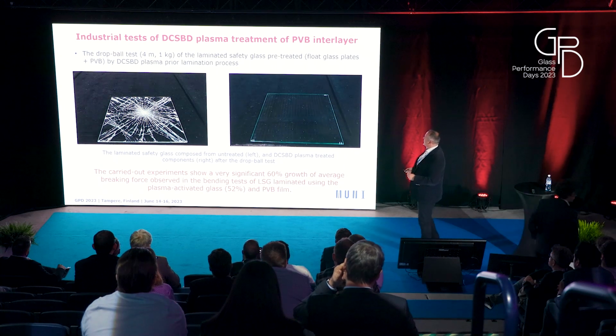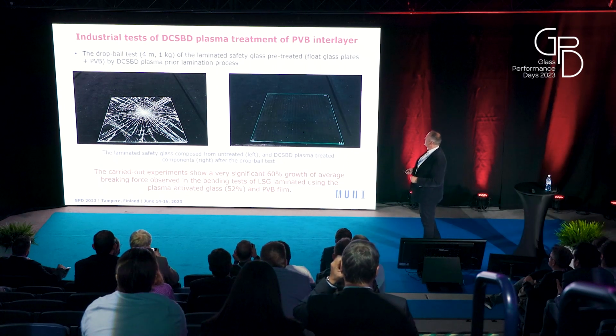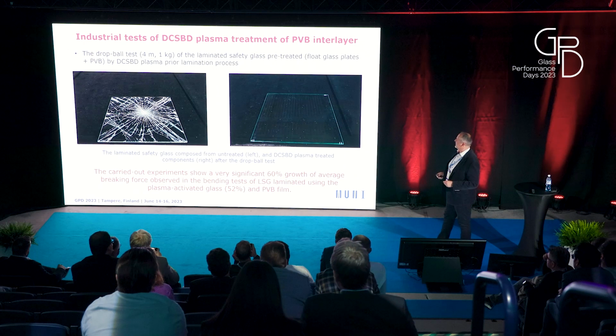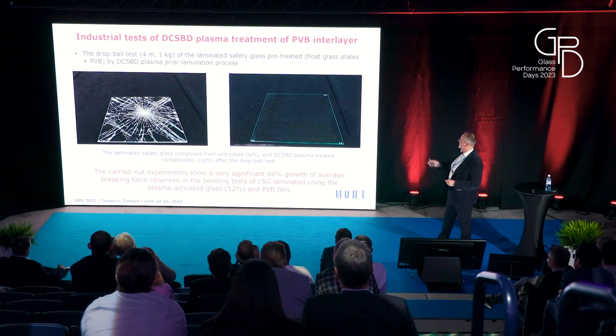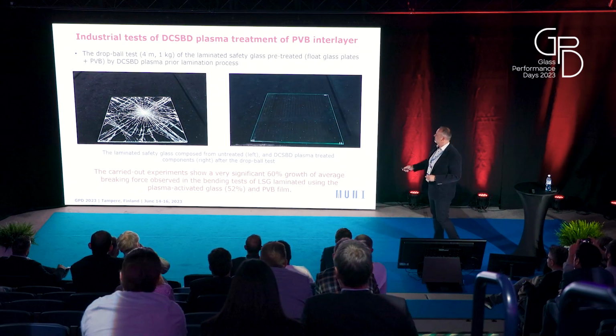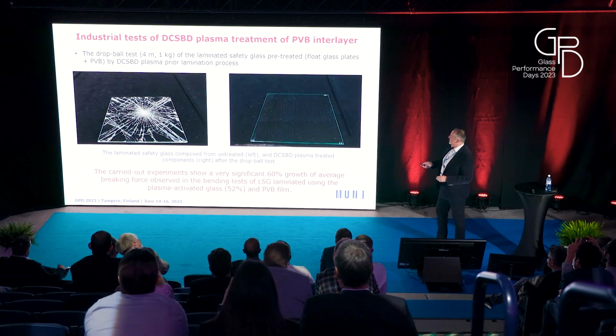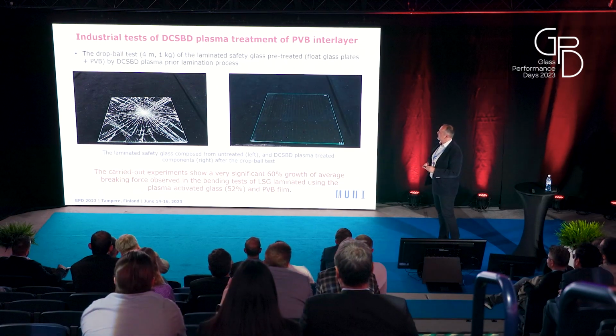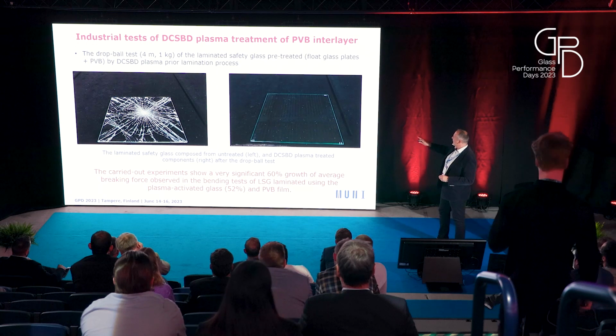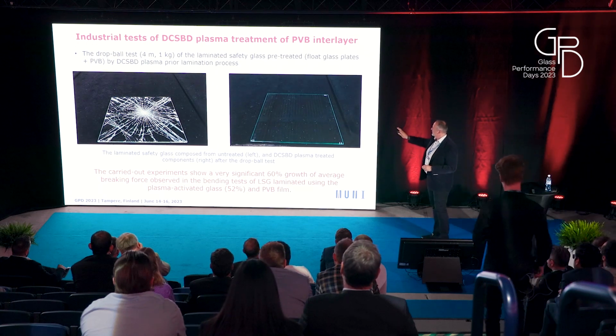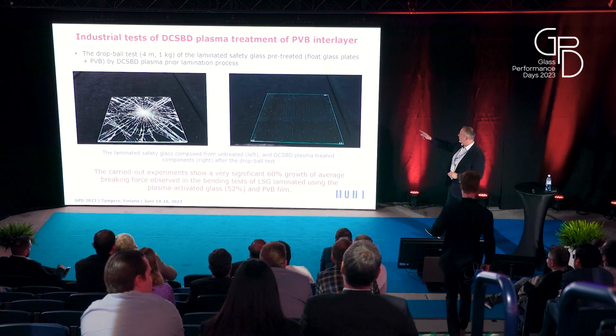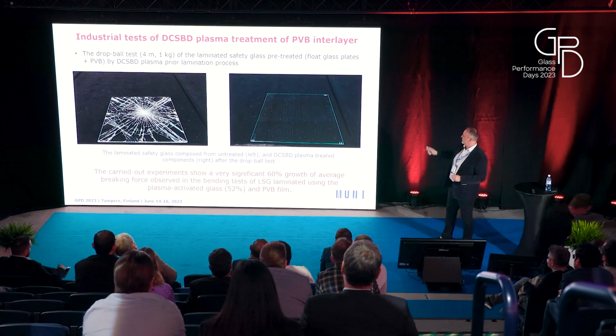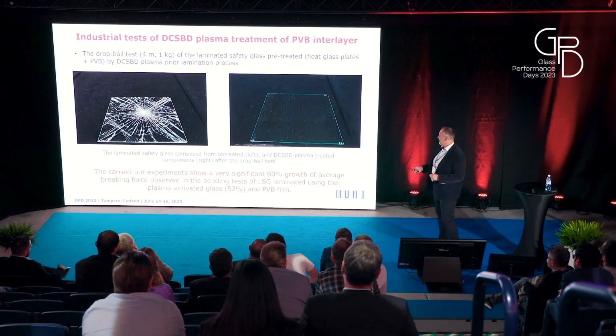As an example of PVB treatment, I can show you these results, the laminated safety glass. On the left side you can see the picture with cracks because of a drop ball test. And on the right side, you can see that there is no observation of cracks. Both glasses and also PVB were treated by our plasma.